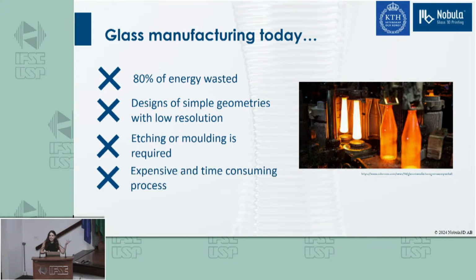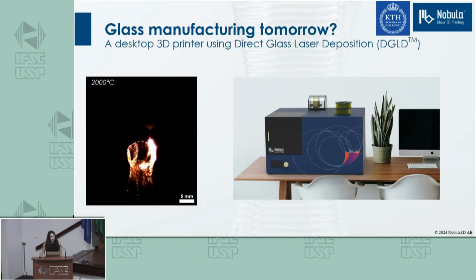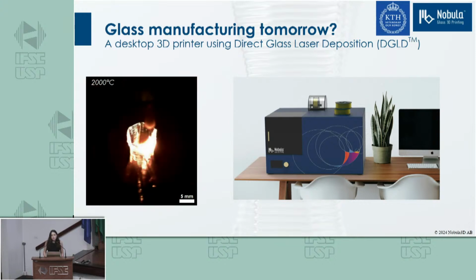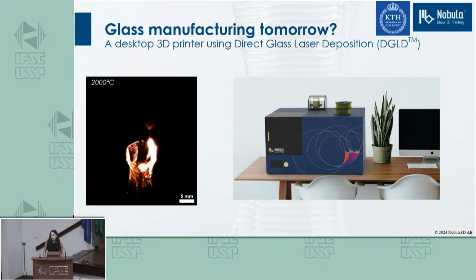But hey, we have found an alternative. I present to you the Nobula glass 3D printer that utilizes the direct glass laser deposition technique to melt a very thin filament of glass up to 2,000 degrees, so that we can deposit glass in a layer-by-layer manner into any shape and form that you can think of. So glass processing is now easier than ever.